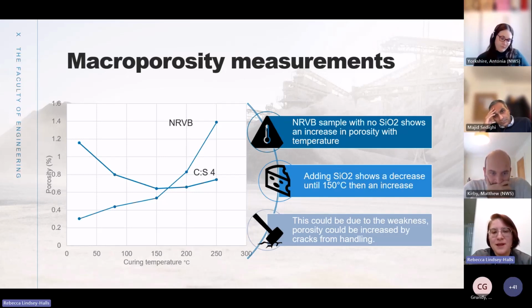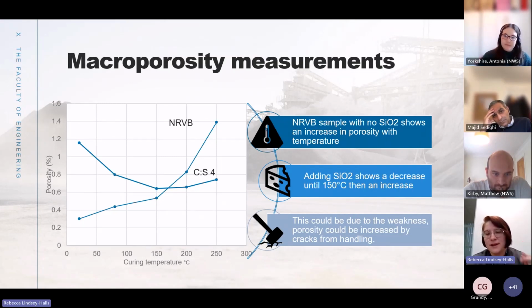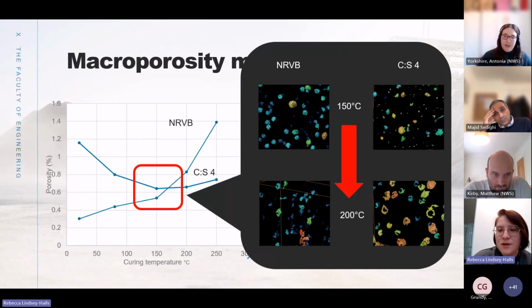So I found that with the NRVB samples, as the curing temperature increases, you get more porosity, which I think makes sense because when you boil a kettle, you get more bubbles. But when you add silica to it, it actually seems to decrease to 150 and then begin to slowly increase again. I'm just going to show some pictures.